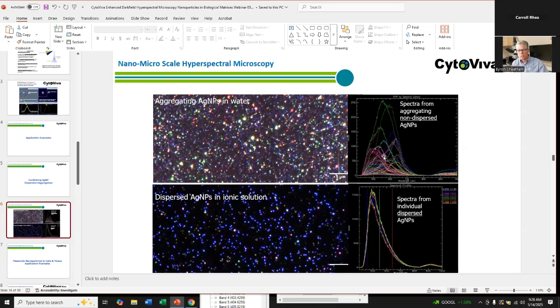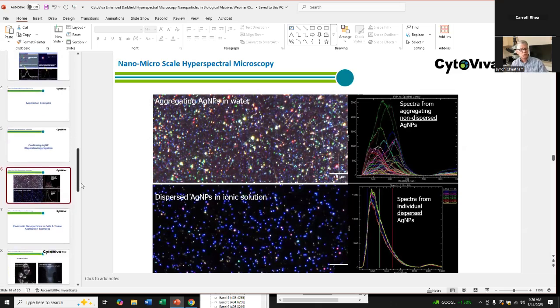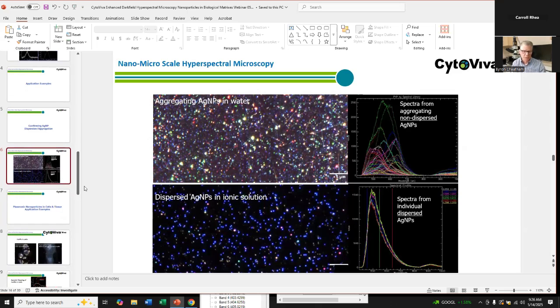And also, if you measure the spectrum of these individual areas of nanoparticles, you see they're very heterogeneous in their spectrum. And that's because of the aggregation that we're looking at, not only in their peak and the width of the peak, but also in the peak wavelength redshifting as well. So they're not very homogeneous in water. They're super homogeneous in this ionic solution that's designed to keep them highly stable and highly dispersed. So this is an example of an application to just look at the nanoparticles in solution and understanding the characteristics of those nanoparticles based on both observation and spectral measurement capabilities.